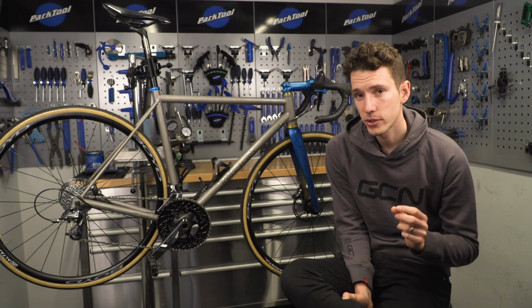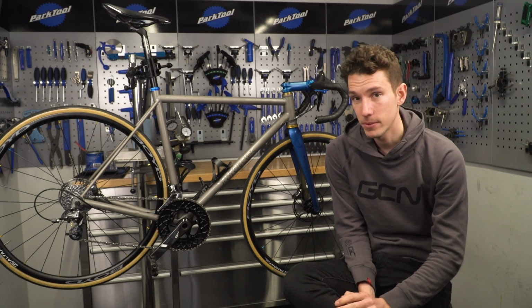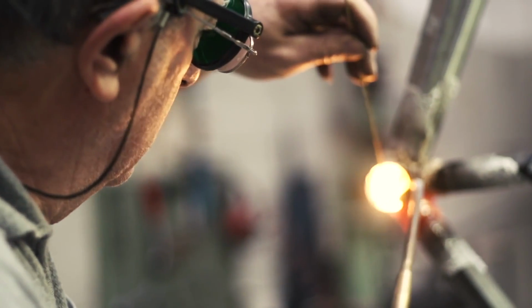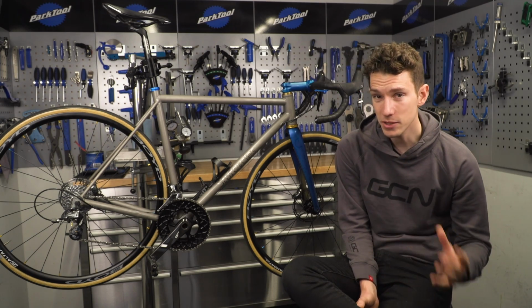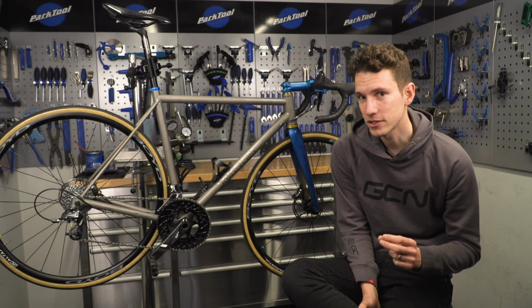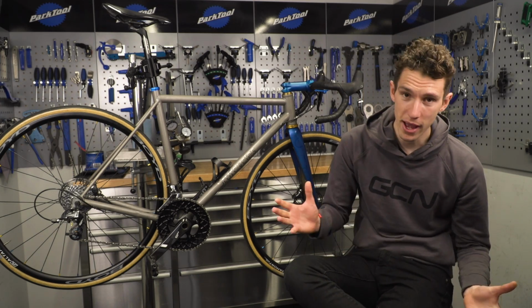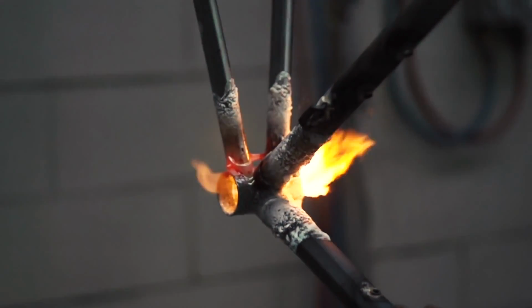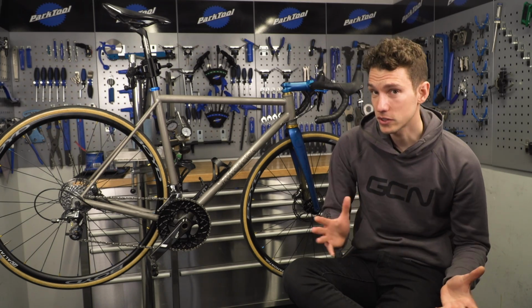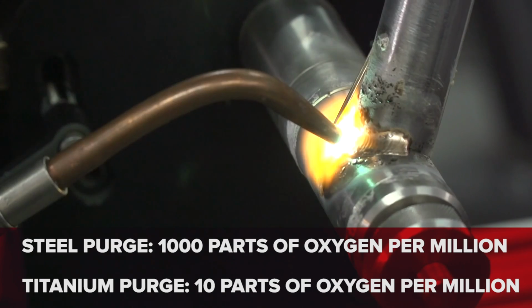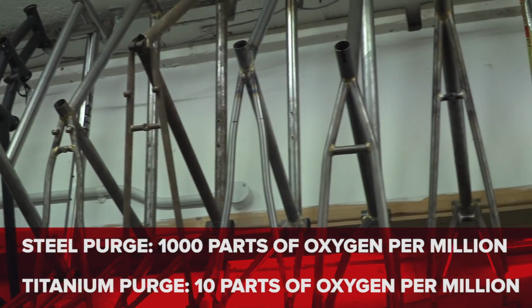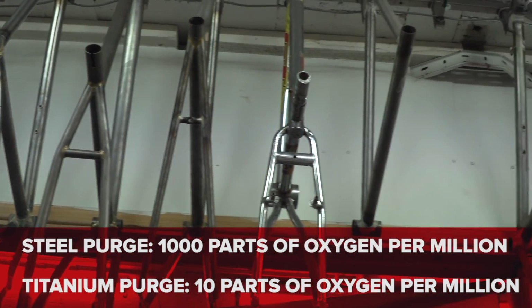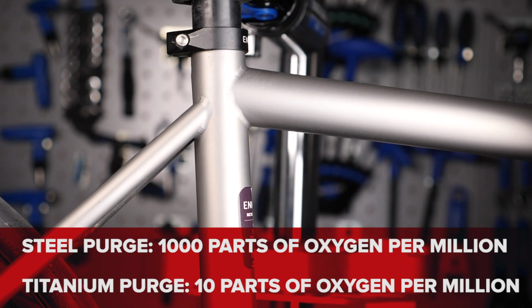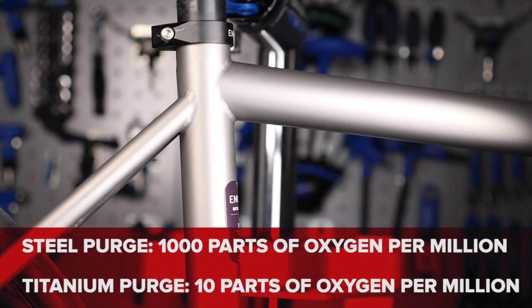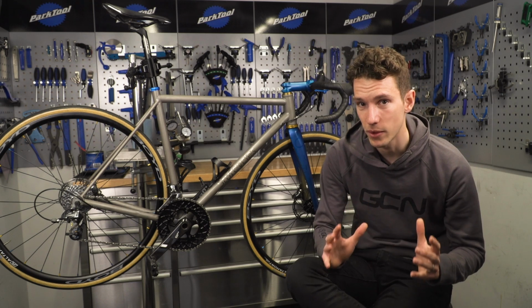Titanium is also a little bit trickier to weld than steel or aluminium, and that's because it's reactive to oxygen at higher temperatures, meaning that when it is welded, it needs to be done in an absence of that gas. Now, to be fair, all metals need to be welded in an inert gas environment, but titanium is particularly sensitive. So to put it in context, if you're welding steel, an acceptable purge, so-called, needs to be about 1,000 parts of oxygen per million, whereas with titanium, it's just 10 parts per million. So that is a little bit of a challenge to a welder.